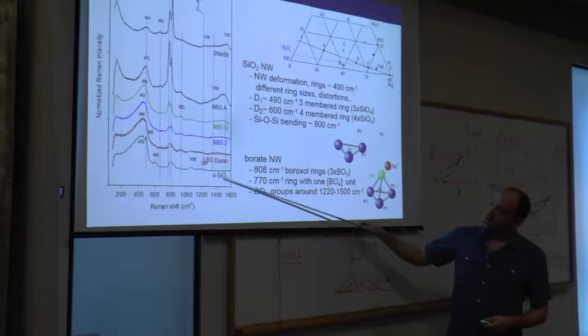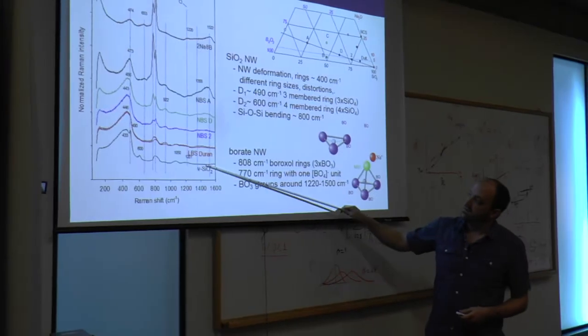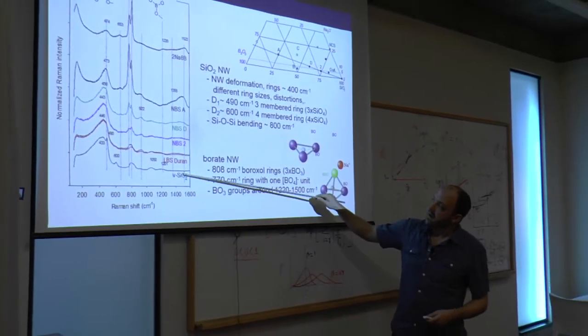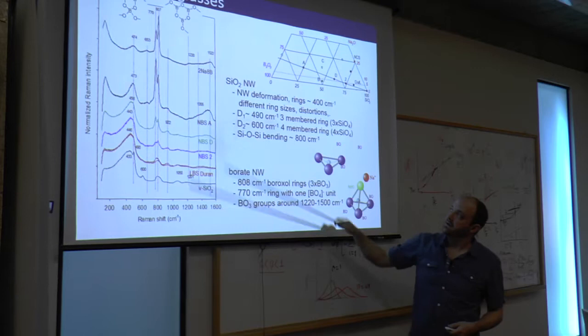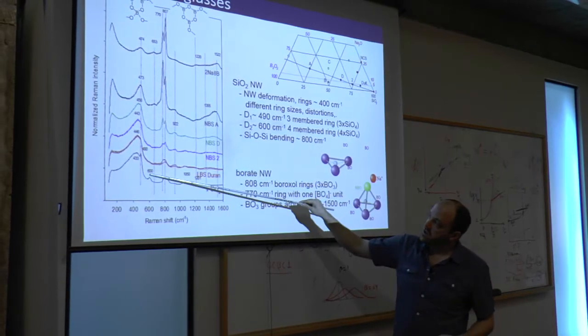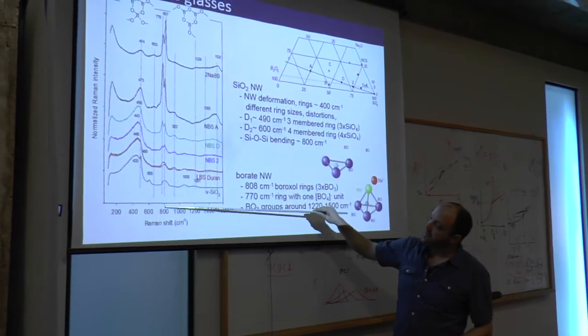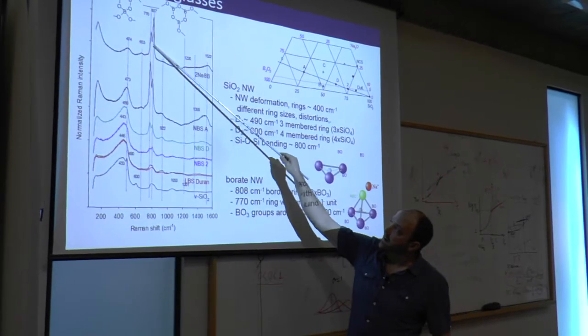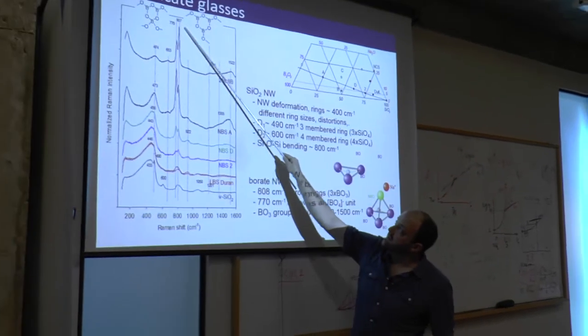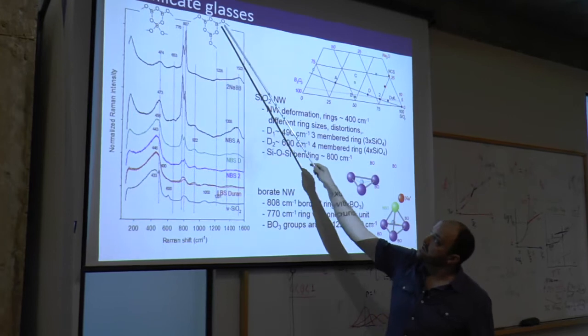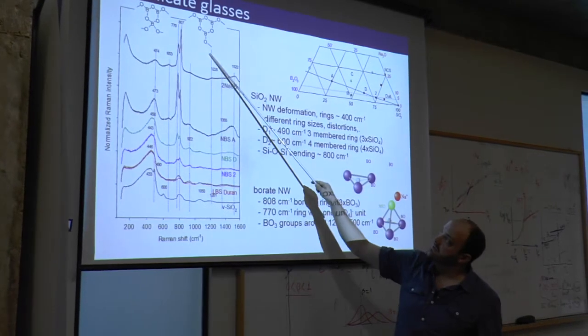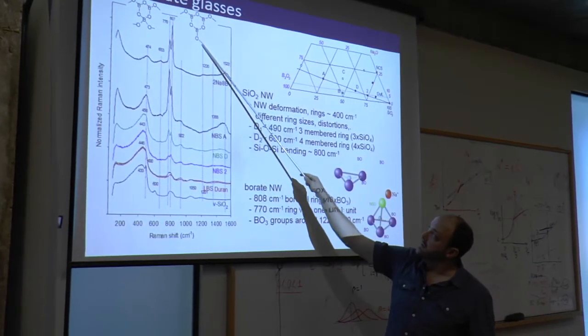Here is pure silica. We've seen this a few times, hopefully you recognize it by now. And as you increase the boron content, you get quite big changes, particularly around 800 here. And these bands at 770 and 807 are associated with 3-member boron rings attached to other boron rings.